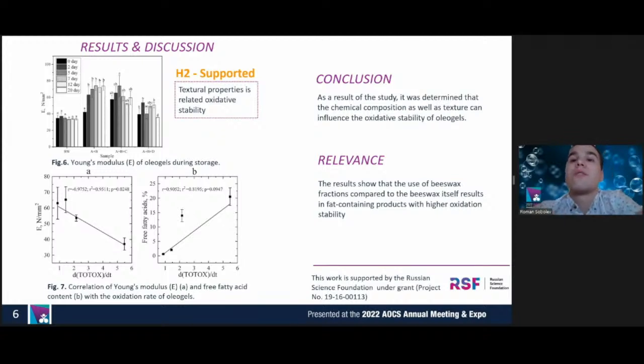As a result of the study, it was determined that the chemical composition as well as texture can influence the oxidative stability of oleogels. The results showed that the use of beeswax fractions, compared to beeswax itself, results in fat-containing products with high oxidative stability. Thanks for your attention.